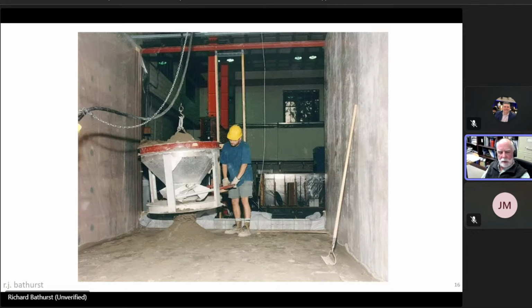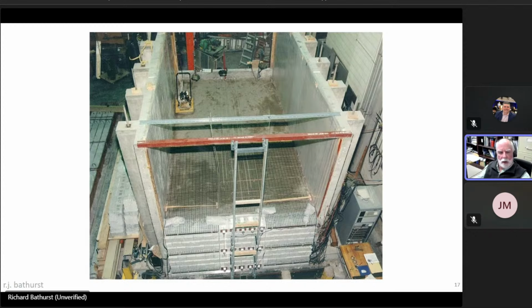Here is a photograph at the beginning of construction where the first lift or two of soil is being placed. And you can see on either side a lubricating, if you like, sidewall system with lubricating oil and vapor barrier to try and create a plane strain test condition to minimize the influence of the test sidewalls. This is the wall when it's about a third of the way up constructed, and you can see the blocks. You can see the reinforcement. These long white things here are extensometers, and there were strain gauges attached as well. Here you can see a walk-behind whacker for compacting the soil.